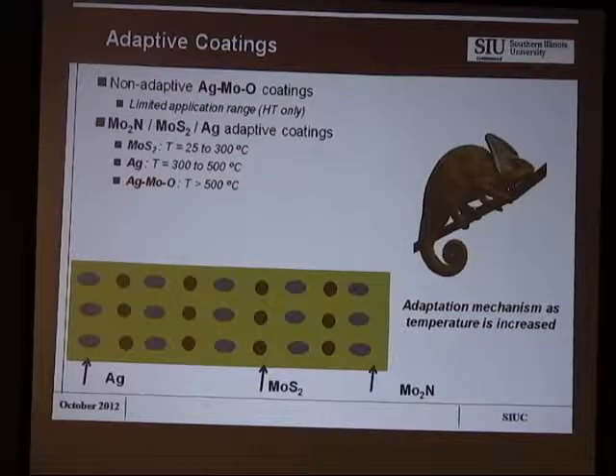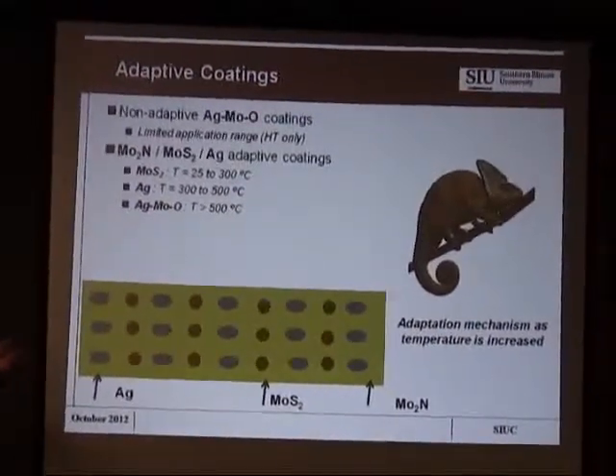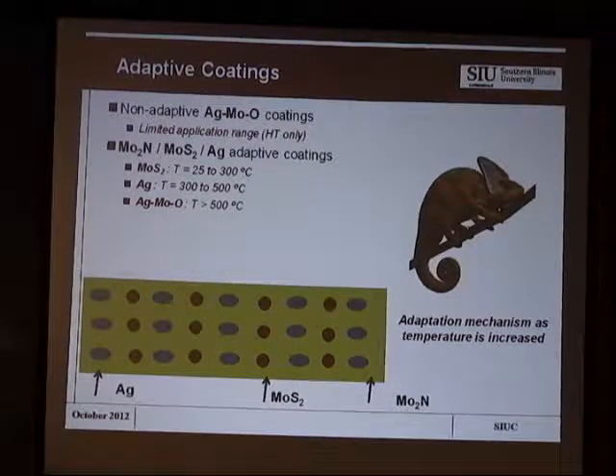Well, the way you do that is by having what's called a chameleon coating. So you mix materials where one of them, for example, here you mix a nitride, a molybdenum disulfide, and silver, so 3 phases or 3 different materials together. One of them works well at room temperature, the moly that I talked about earlier. The other one works well up to about 1,000 degrees Fahrenheit, so works in the mid-range temperatures. And then finally, you can also form silver molybdate if the sample is hot enough.